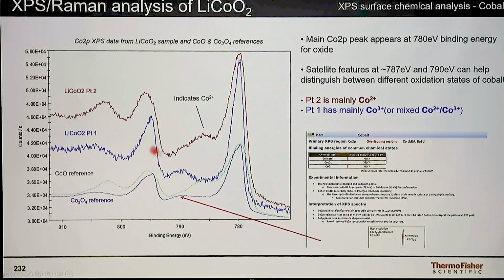So again, if we look at the cobalt chemistry, we can see that there's actually a variation in the oxidation state between the 2 points. So at point 1, we've got mostly cobalt 3+. Point 2 is mostly cobalt 2+, and that's really indicated by this satellite. You can see there's not a big difference in the peak position. It's the presence of these satellite features, which are, particularly for transition metals, as the oxidation state changes, you tend to see other satellite features appear and disappear, which are quite diagnostic for understanding the surface chemistry.